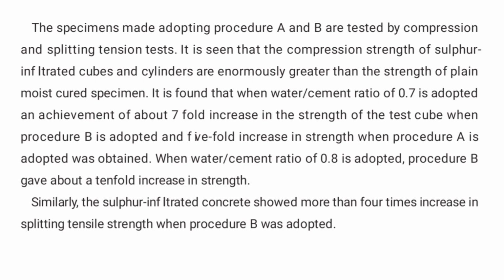It is found that when a water cement ratio of 0.7 is adopted, about a 7-fold increase in strength of the test cube is achieved when procedure B is adopted, and a 5-fold increase in strength when procedure A is adopted. When a water cement ratio of 0.8 is adopted, procedure B gave about a 10-fold increase in strength. Similarly, the sulphur infiltrated concrete showed more than a 4 times increase in splitting tensile strength when procedure B was adopted.